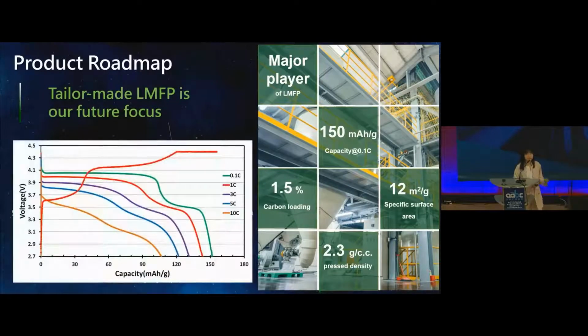So here's the half-cell testing data of our material. Our material has a specific capacity of 150 milliamp hour per gram. You can see that the power capability is very superior. And the specific surface area is about 12 meters square per gram. And the maximum press density is 2.3 gram per cc. You can also see that the carbon loading is very low, so you can fully utilize the capacity of the material.